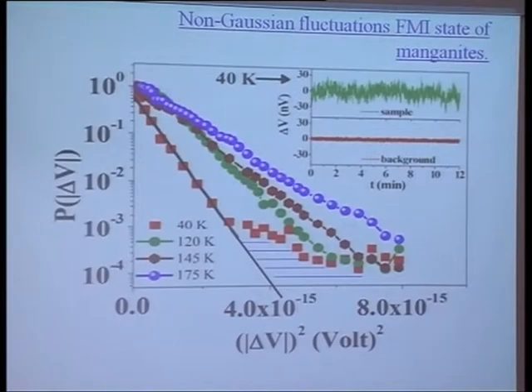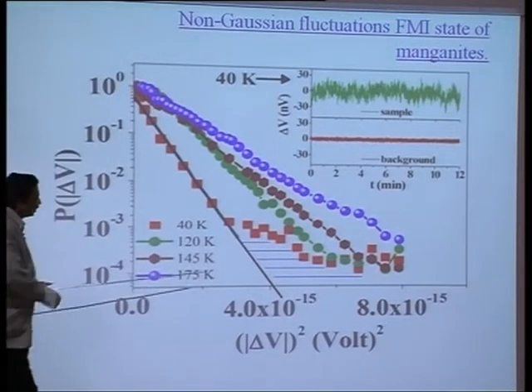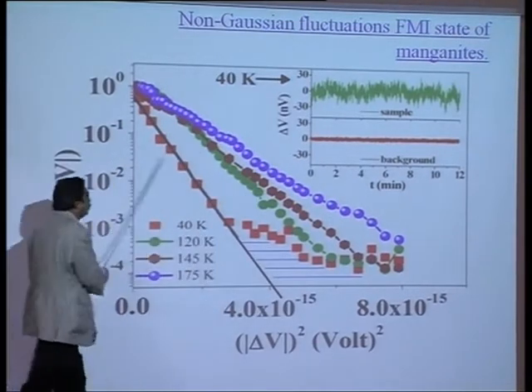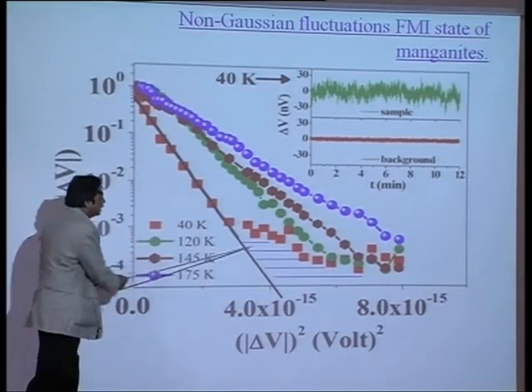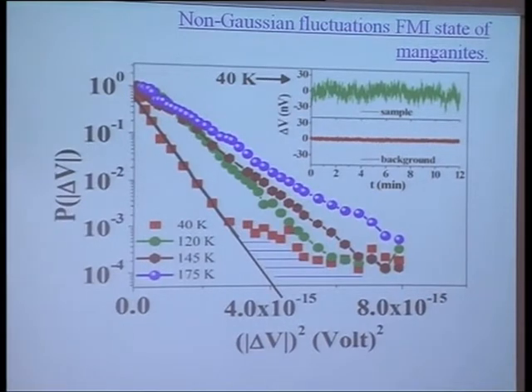Now, let us see what we see there. Here we have plotted in the way Gaussian fluctuation should be seen. You can see at high temperature it is Gaussian, but if you go to lower temperature, this tail comes up, and this is a very distinct tail. Those who are in this business know that you can change this quantity by the bin size, that is, how large a delta V should be used for counting.